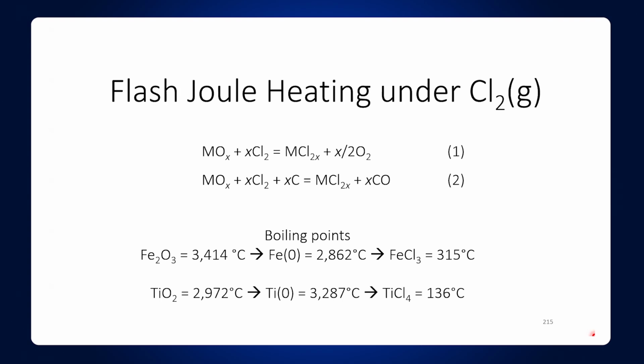But what it capitalizes on is the free energy of formation of the metal chloride. And as soon as the metal chloride forms, boom, it just distills out. So let me show you this. The idea is this. You can take a metal oxide and react it with chlorine gas to form the metal chloride. Or if the metal oxide won't react directly with chlorine, you can add carbon to it, and the carbon will reduce the metal oxide to either a lower valent metal oxide or a metal, just a metal zero, a metallic system. That will then react with the chlorine to form the metal chloride. So you have these two possible routes. One is a chlorination, the other is what's called a carbochlorination reaction, to make the metal chloride.